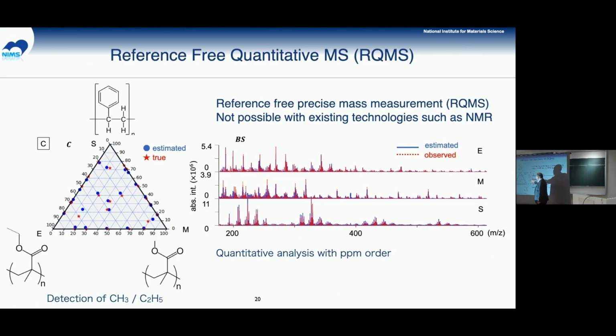So we performed an evaluation of the mass spectroscopy. First we made a mixture of polystyrene, PMMA and ethyl methacrylate. We just mixed them together. The red star indicates the true data, and blue is the estimated one, indicating the NMF result. They are almost consistent, in good agreement. That means our calculation, the machine learning, is reasonable and reliable.